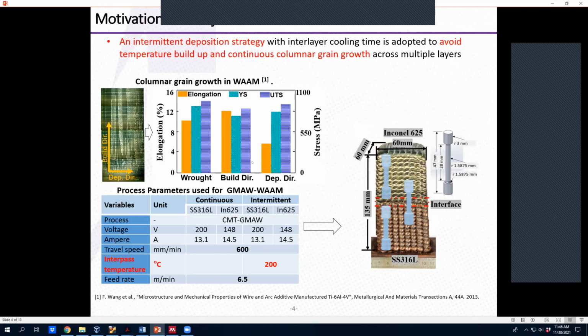For this strategy, during the deposition of successive layers, we allow the previous layer to cool down to an intermittent temperature, or interpass temperature. Through trial and error, we have figured out that 200 degrees intermittent temperature works best for this approach. Here are the EBSD grain maps showing the grain size transition as a result of the intermittent deposition strategy. As you can see, we're working on two materials, stainless steel and Inconel. In both materials, you can see the columnar grains transitioning into fine equiaxed grains. This phenomenon is generally called columnar to equiaxed transition.